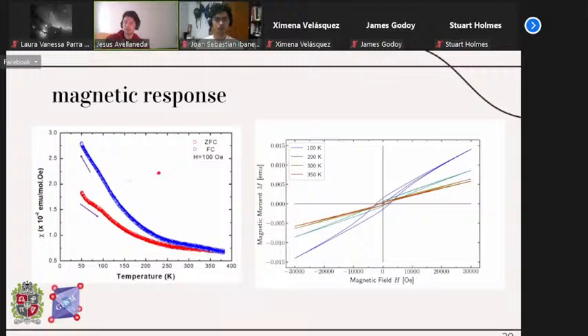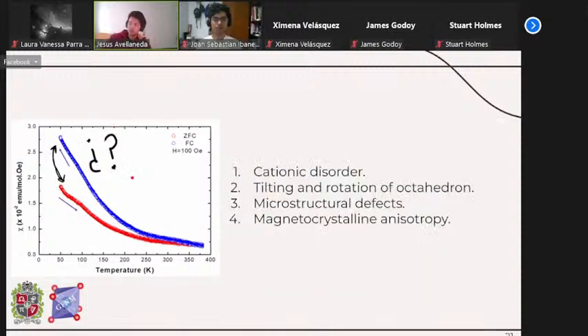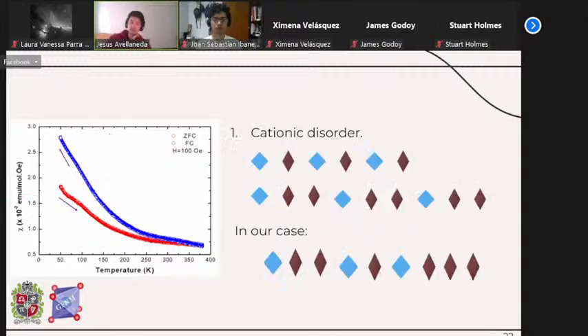Basically, the figure shows us two curves, the ZFC curve and the one above it, the FC. The curves indicate a non-reversible process, which could give us the idea of high hysteresis. I will expand on this later. But basically, the general idea is that the distance that separates these curves can tell us that the reasons for the ferromagnetic behavior are fourfold. Basically, we have cationic disorder, tilting and rotation of the octahedron, microstructural defects, and magnetocrystalline anisotropy. So for the first one, the cationic disorder, we initially could expect a cationic arrangement between lanthanum and calcium, but with titanium and iron, that was not the case.